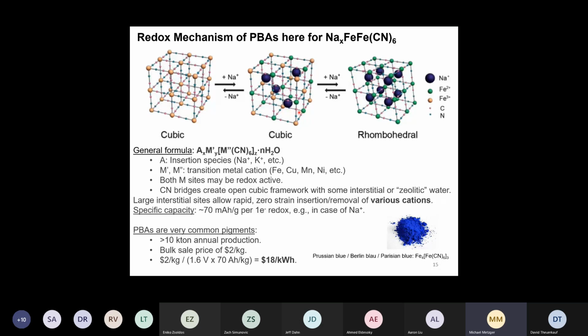And yeah, I think it's a question probably of how far you take your charge compensation in the material, whether you want to bring all the ions, in this case, the iron atoms, to a 2+ oxidation state. I don't want to speculate too much as to why then you have these structural problems with calcium, but you can imagine maybe 2+ ions, maybe there's some place exchange happening. So it's really, I think, not fully understood, but the material cycles very well if you go up to this sodiation state. If you go further, then you get into trouble.